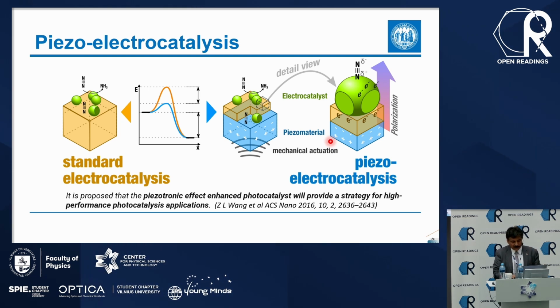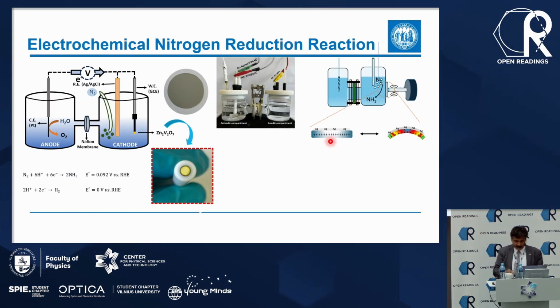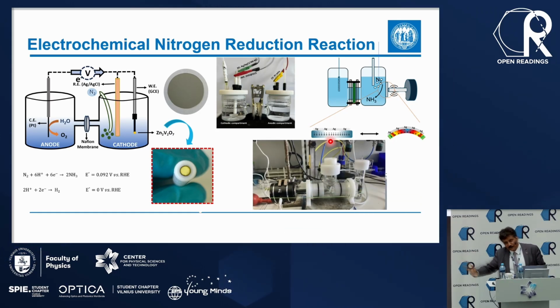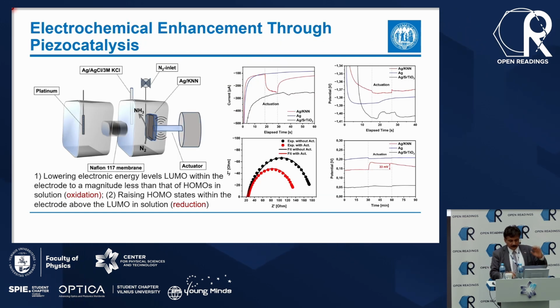So Naina, in her PhD, is now working on this. What we are doing is taking a piezo substrate, putting catalyst on that, and mechanically actuating it. And by doing so, you convert a classical electrochemical cell into piezo. You can see that it's very fundamental. You basically have a mechanical actuator here, and this actuator is then helping. At some point it will come, I was told, yes, so here. So now you are having a continuously vibrating electrocatalyst. The condition is that the electrode is really fixed, it's not falling in the solution, and then you can create a small piezo potential that again helps you to have a better catalyst.